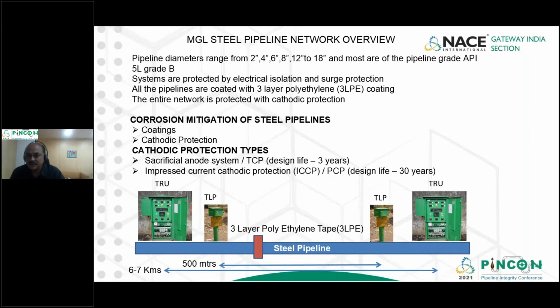Our systems are protected by electrical isolation and cathodic protection. All pipelines are coated with 3-layer polyethylene coating, and we do have some sections of pipeline with fusion bonded epoxy, but most of them are 3-layer PE. The entire network is protected with cathodic protection. So corrosion mitigation in steel pipelines is by coating and cathodic protection. The cathodic protection types are sacrificial anode, which is known as temporary cathodic protection with a design life of 3 years, and the impressed current cathodic protection system, which is a permanent cathodic protection with a design life of 30 years.